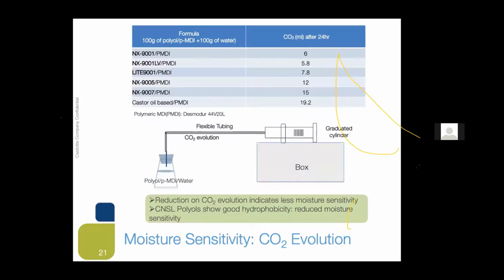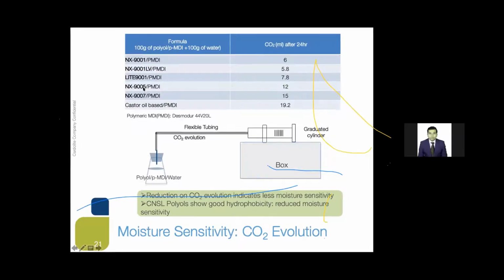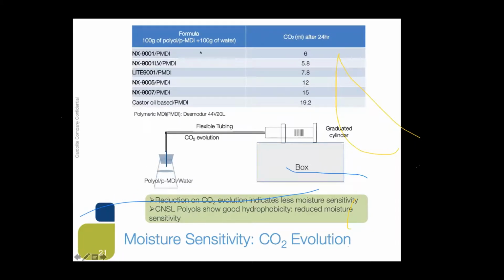Yeah. And this slide shows some moisture sensitivity testing data. How did we do it? We take the polyol with the isocyanate. Sometimes polyol will react with isocyanate, and sometimes isocyanate reacts with the water. So for this data, we checked the CO2 evolution test. What is meant by CO2 evolution? The lesser the value, the better. If you look at 9001, it shows only 6. It means it has less moisture sensitivity because of the hydrophobic nature of this 9001 compared to the castor based polyol. Other series have almost higher values. So it shows less moisture sensitivity of our CNSL based polyol 9001.